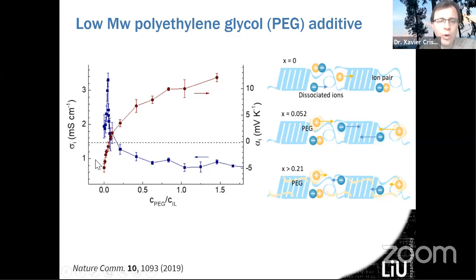So if you follow here, first this curve in red is the Seebeck coefficient of the ions. I told you at the beginning, before we add this polyethylene glycol, we get something like -5, and these are the anions that are mostly moving.